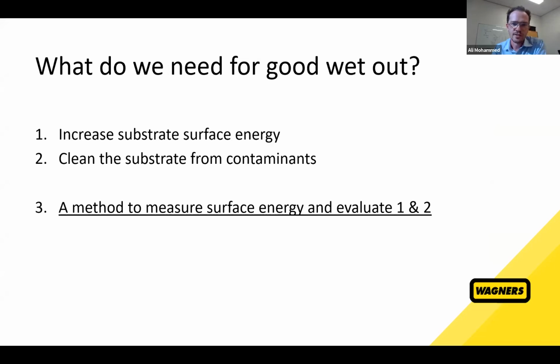So just to summarize the last couple of slides, what do we need for good wet out of our adhesive onto these substrates? We want high surface energy of our substrate so that the adhesive flows across. We want a clean substrate, so no contaminants on the surface. Now, if we achieve both of these things, we should be getting closer towards a good bond. Obviously, there's a few other factors there as well. But how do we actually assess whether we've achieved a higher surface energy and a clean substrate? How do we assess and evaluate our surface that we're about to bond to?